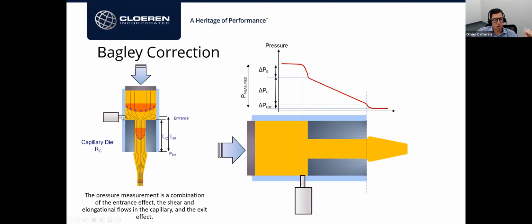However, the measured pressure, because of the location of the sensor, is a combination of different features. And this graph shows here the different features. So in this region, we have an entrance pressure, which is very strongly dependent on how elastic the melt is. Okay, this can be a small value or it can be a great value. Then we have the capillary pressure, which is mostly driven by the shear flow and a little bit of elongational flow as well. And finally, we have an exit pressure, which because of the swell and also the elasticity of the melt can be non-zero. But in general, this pressure is fairly low.